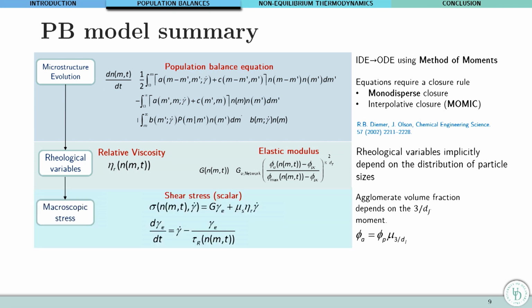So if we want to extend it and reduce the number of parameters, this is where the microstructure comes to be of importance. And using the population balance, just pay attention to the fact that there is a fundamental equation that describes the population of every size of aggregate, M representing the number of primary particles that constitute an aggregate. And this expression is an integral one which involves contributions which result either in the restructuring or the breakage of those structures, with well-specified kernels from previously developed expressions based on the collisions between different aggregates.